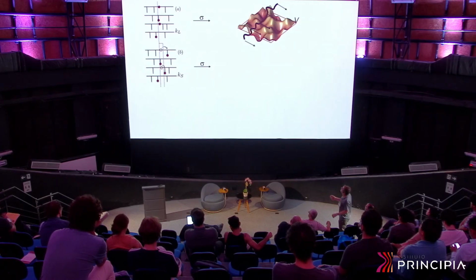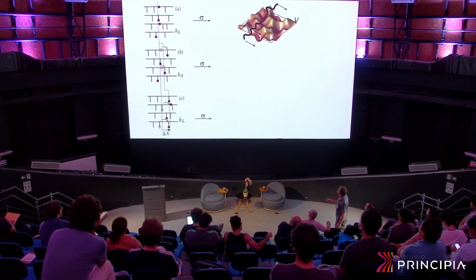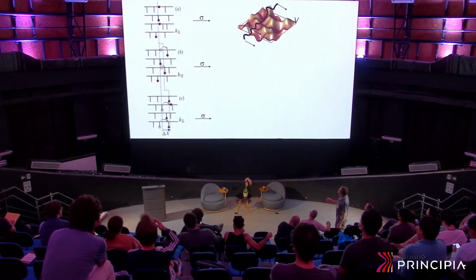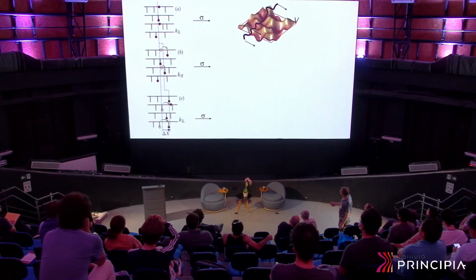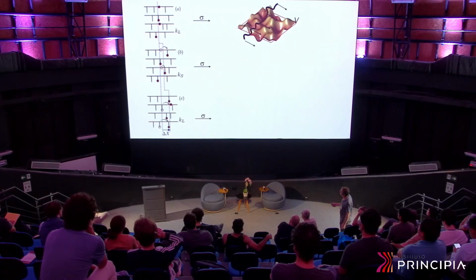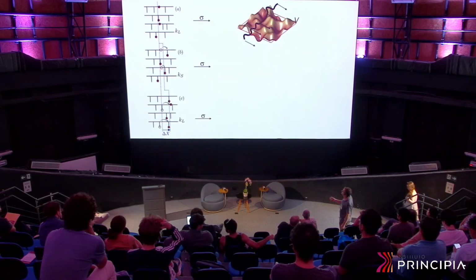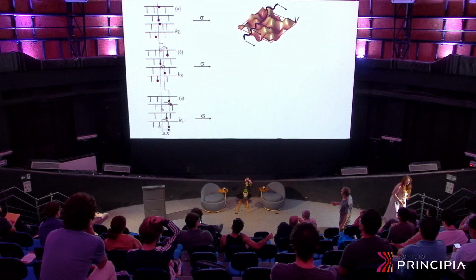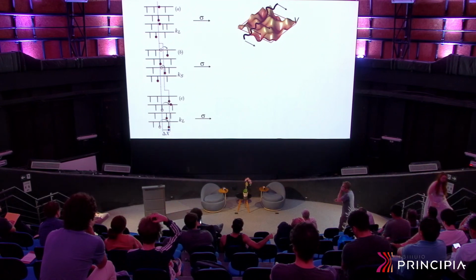When I go back to the original value of the spring constant, essentially what happens is that the particles that jump to new potential wells are not able to return to their original position. The particles that are leftmost in the plot are those that feel the largest force, and some of them jump to new positions to the right. Now the average position of the system is here, which is shifted with respect to the original position, although the value of the spring constant is the same here and here. The system has moved, has deformed, okay?